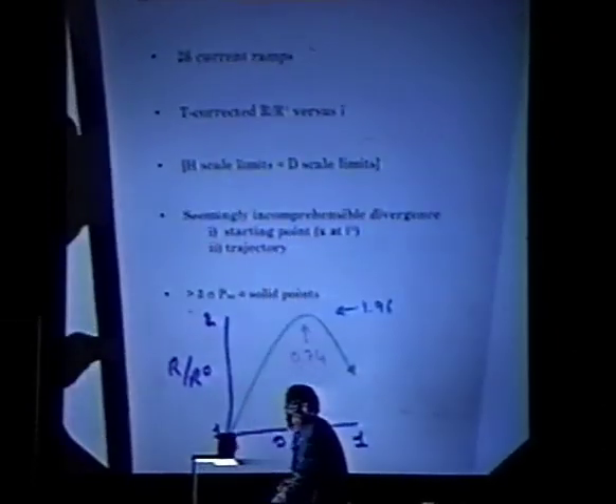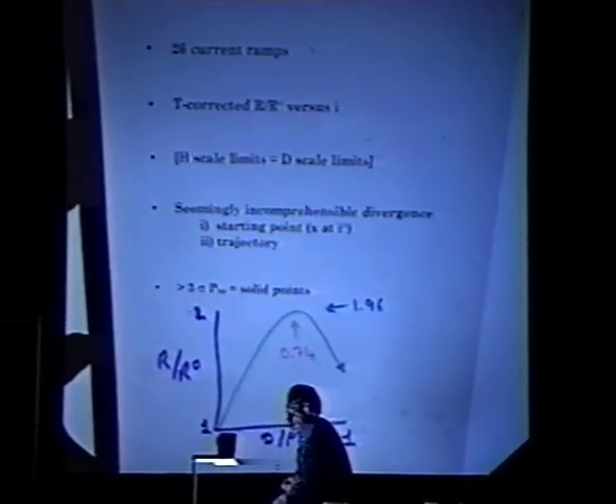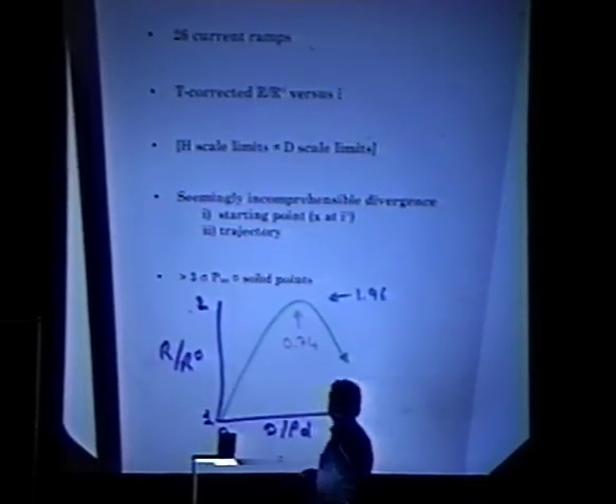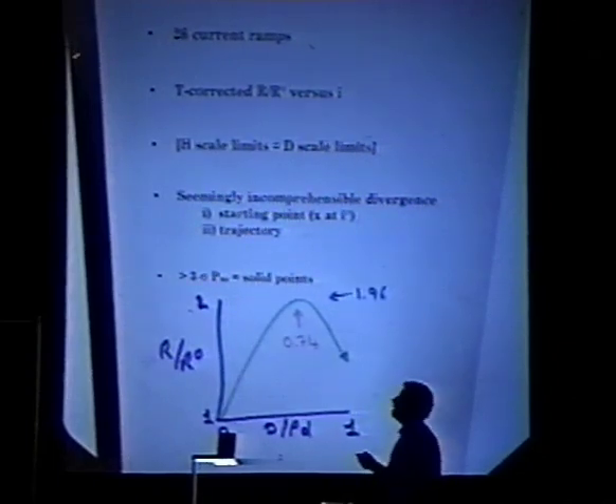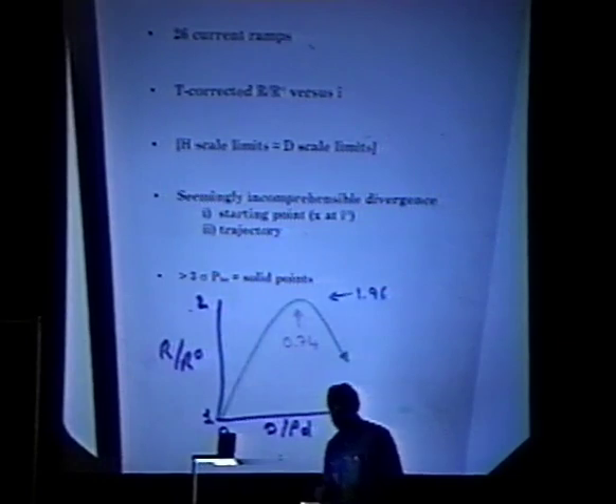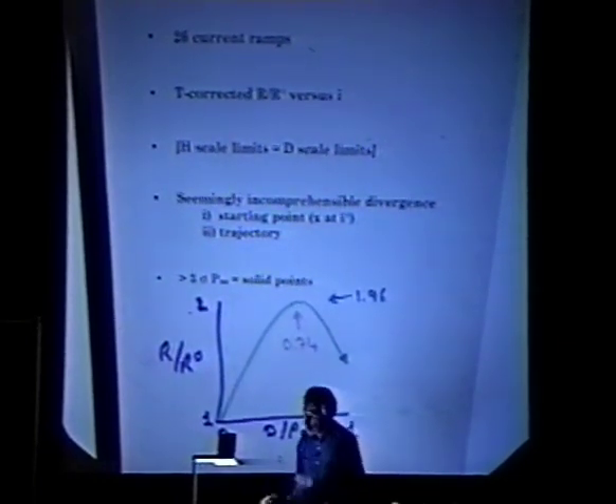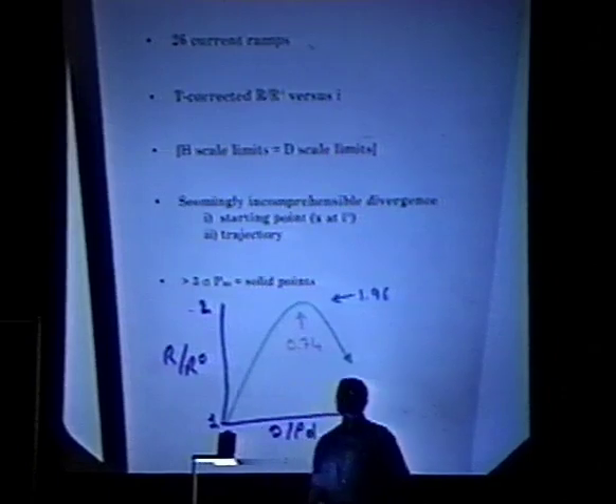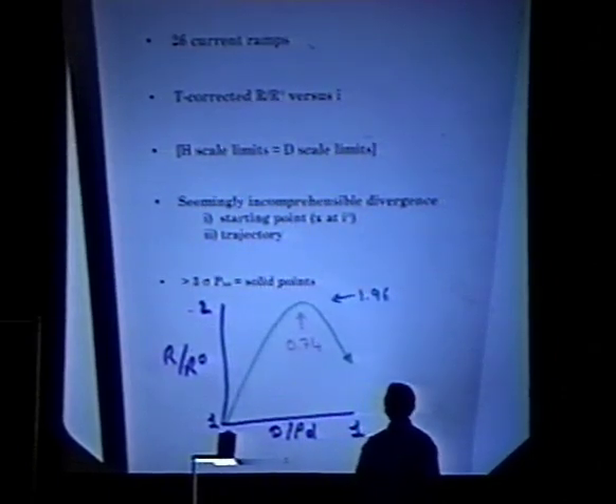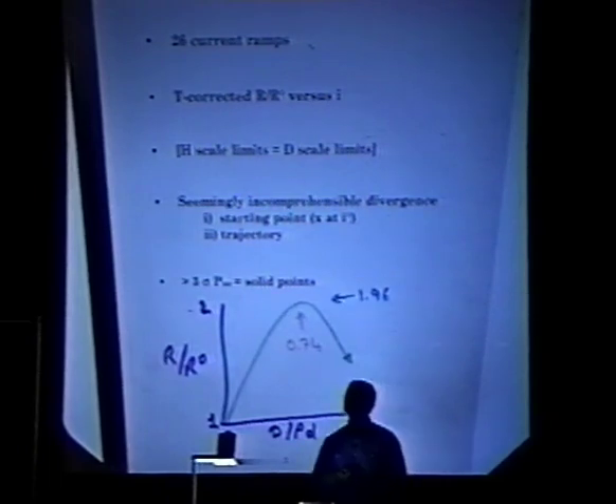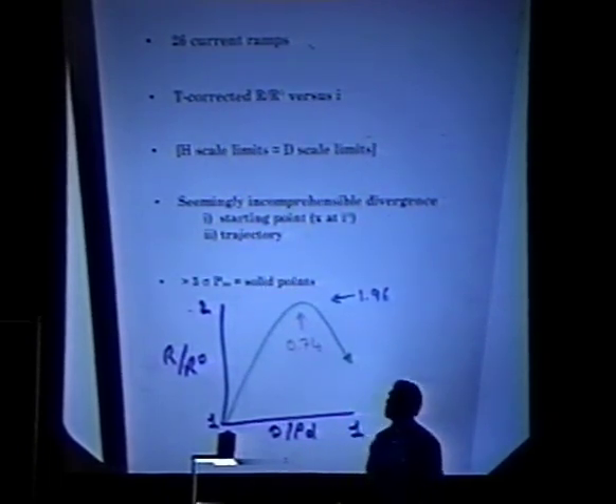What I'm going to describe is a series of experiments designed to really institute the conditions that we think we need: high deuterium to palladium loadings, as measured by the resistance ratio, at high currents for long times. What I've done is scanned through the data that we've accumulated over the 8 or 9 years that we've been working in this field, and selected 26 nominally identical current ramps, increasing current, measuring the resistance ratio.